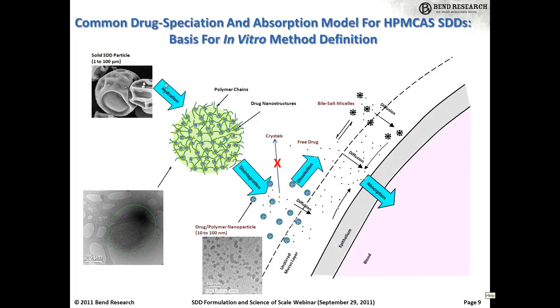What's shown here is that the SDD particle comes in, it begins to hydrate as the polymer is soluble again in the intestinal fluid, and then it dissolves and oftentimes casts off these colloidal drug polymer species, which are shown here. As well, of course, you get rapid dissolution from this high surface area material to the free and dissolved drug, and that's also in equilibrium with bile salt micelles. So the free drug and the bile salt micelles diffuse across an undisturbed mucous boundary layer in the intestine, where the free drug is absorbed. And then the SDD and the colloidal species can continue to rapidly source that free drug as it's depleted through absorption.